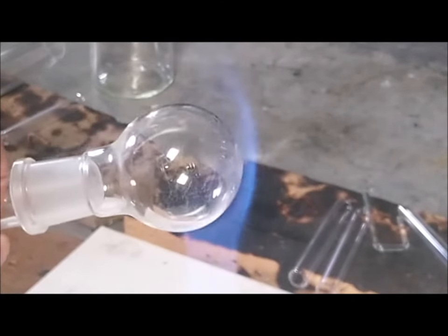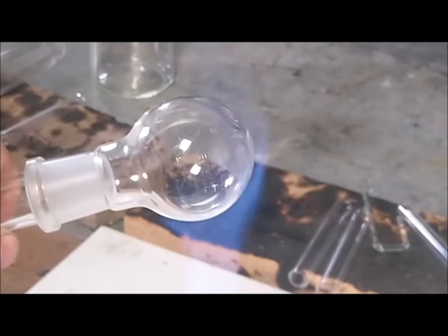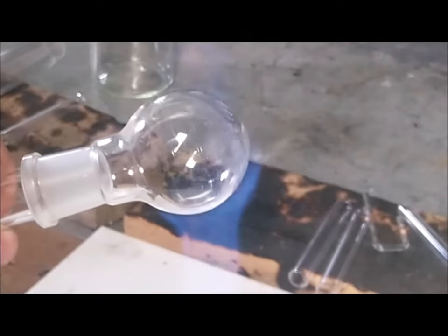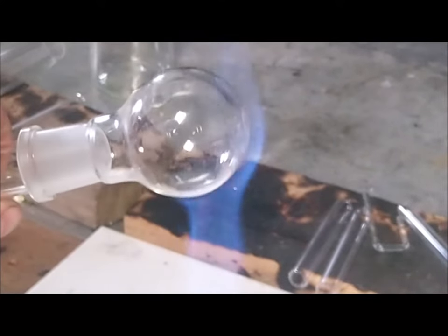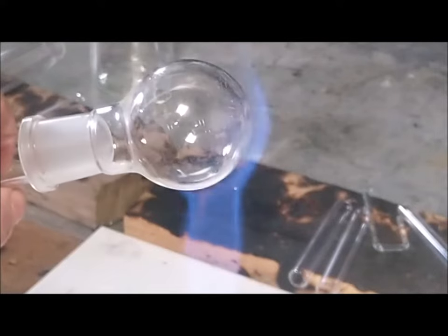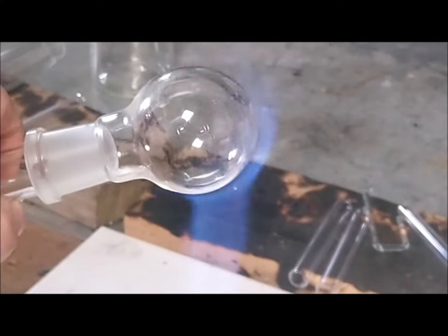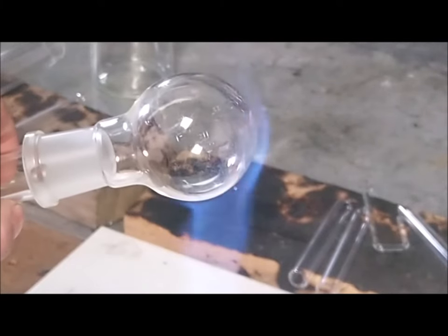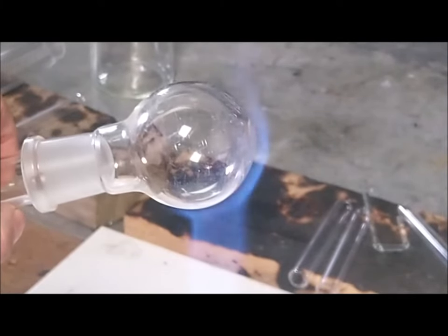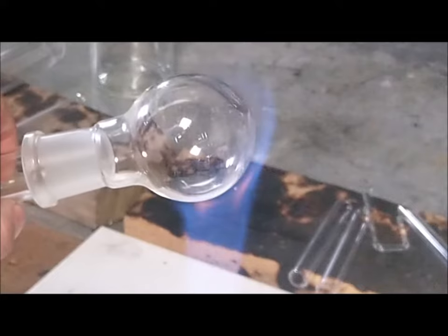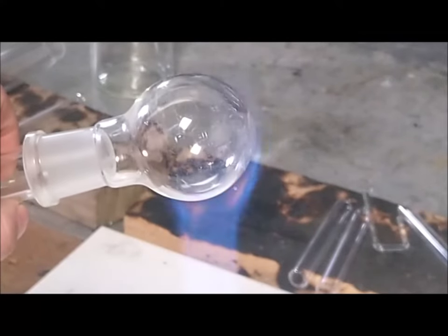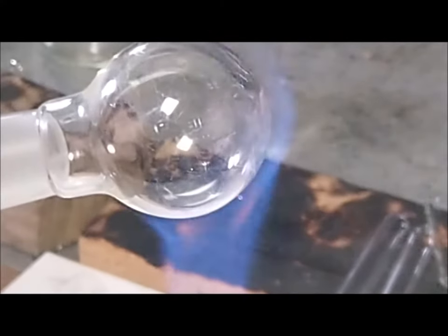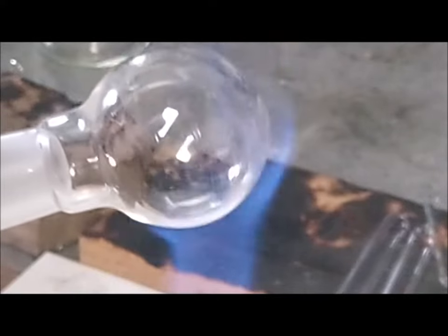and that's really the reason why Cody's lab failed, he just didn't warm everything up first. If you get it up to a high enough temperature you can get that flame onto the crack and you should be able to make it just disappear it should just you should just watch the crack melt back in and if the glass is clean then it'll be an invisible repair